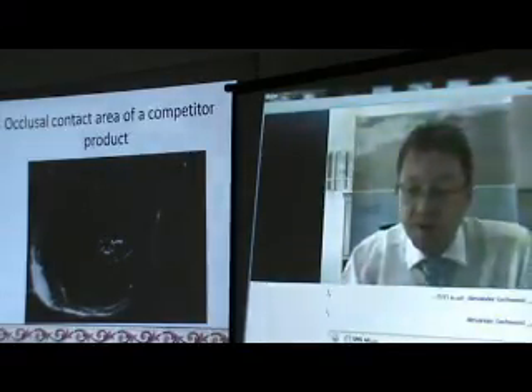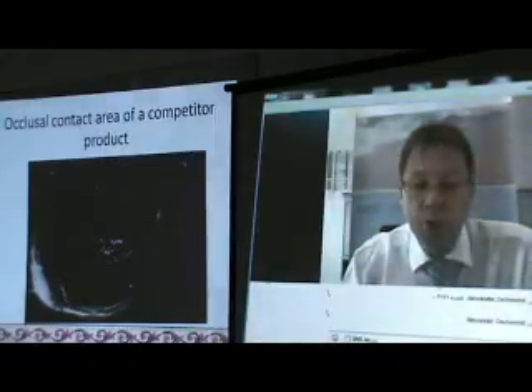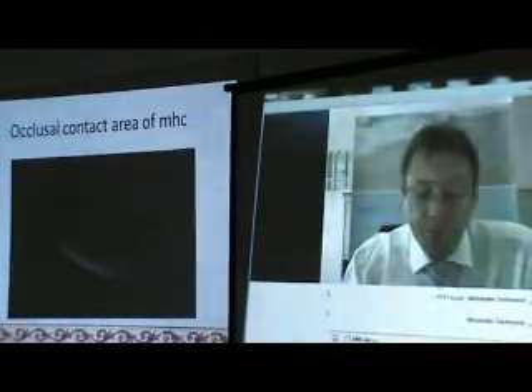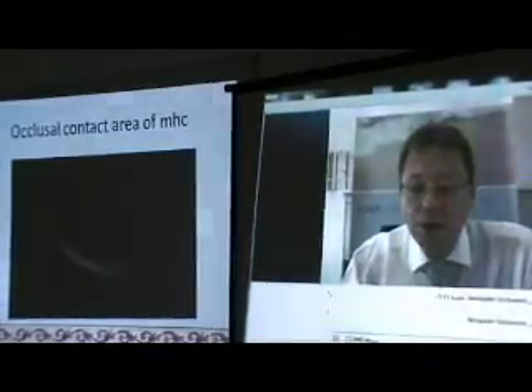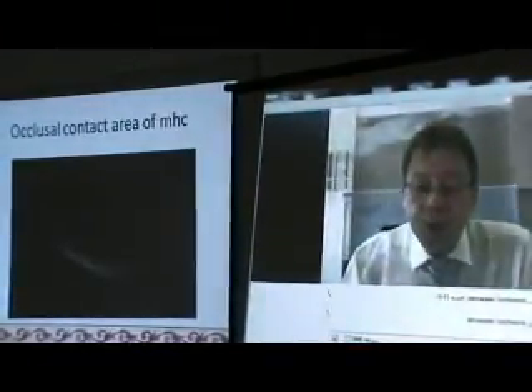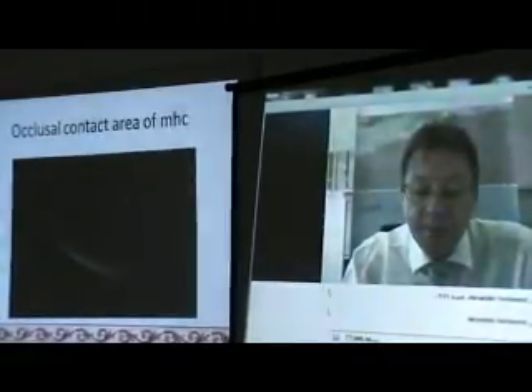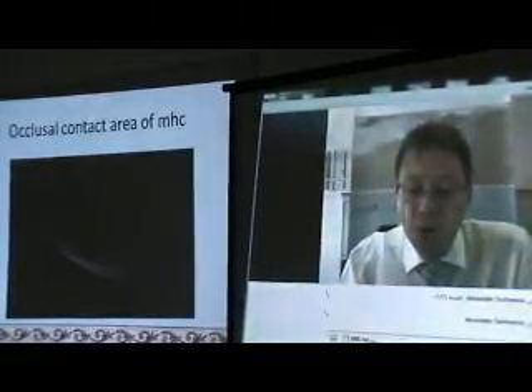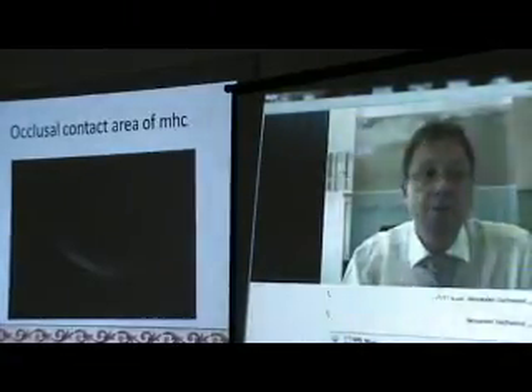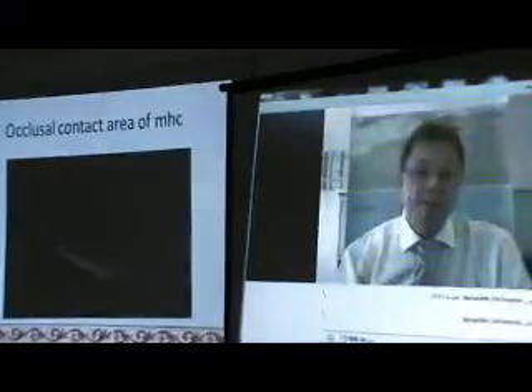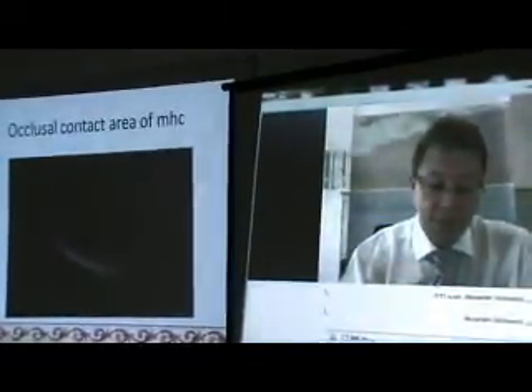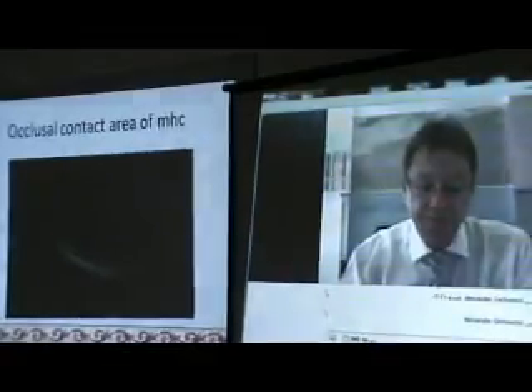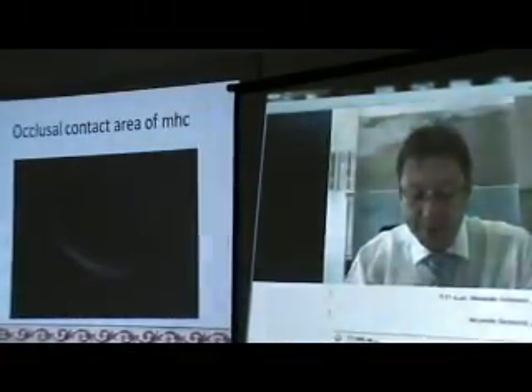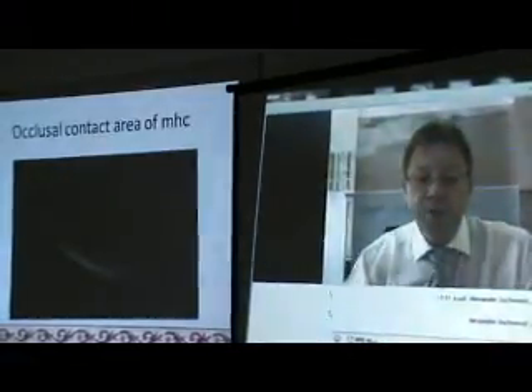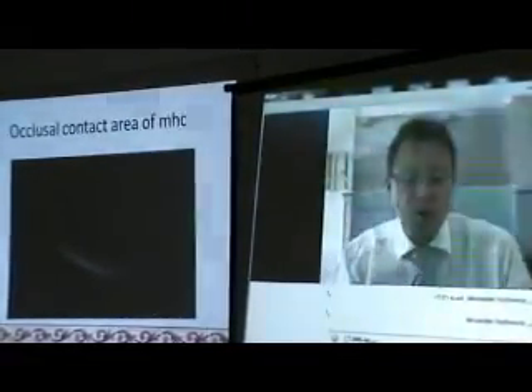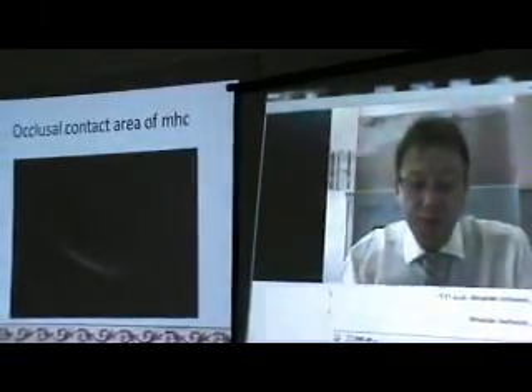On this first picture, on slide 23, you see the occlusal contact area of a standard composite after this mastication simulation in the university. Here you can see, in the middle on the top of the picture, there is a small bubble, there can even be air inclusions. At the lower part, you can see that there can be fractures, which is due to the mastication. So in general, the result here is not very appealing due to the fractures and air inclusions which have been caused by the mastication process.